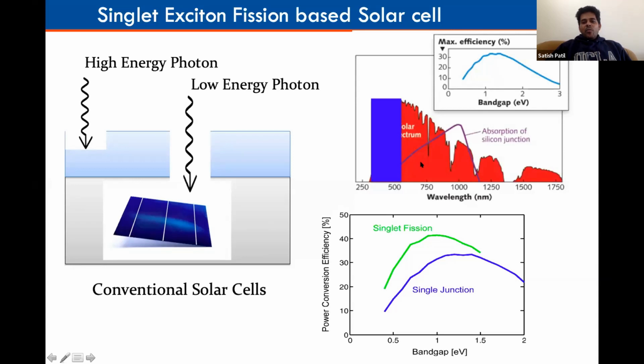However, the blue part of the spectrum is very high energy photons. They are all loss mechanisms. So you have to counter these loss mechanisms by putting some organic dye. It is simple to do. You just take a silicon solar cell and you can coat a very thin layer of organic dye which only absorbs the blue part of the spectrum.